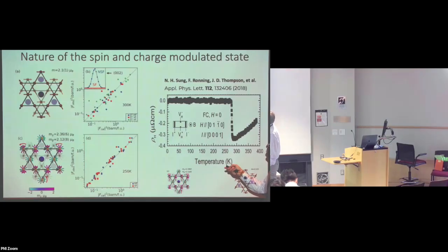Okay, so the point is that I have three vectors here, which are adding up to 0. They form a triangle, and they add up to 0. However, we are in a crystal structure, and these spins are actually oriented along different directions. These spins point between manganese sites. This spin points between two manganese sites. This one points between two manganese sites. But this spin is the same spin as this one, for example. It points between two sites which have a tin atom on them.